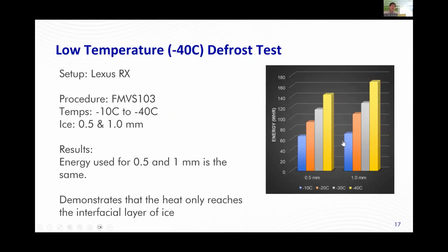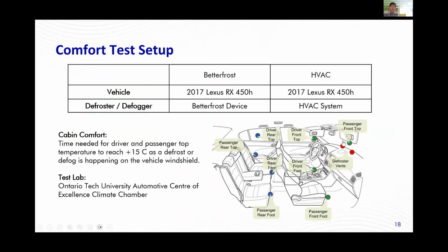We've also tested this down to minus 40 C at the Ontario Technical University's ACE climatic chamber in Oshawa, Ontario. And at minus 40 C, we've removed 0.5 millimeter and 1 millimeter of ice. What's really interesting about this, if you look at the amount of energy to be removed at the two different amounts of ice at the different temperatures, you'll see the energy is almost identical. And that is a sign that our technology is working, that the heat is only reaching that interfacial layer. So we have other tests where we show the amount of energy necessary to remove the ice is not dependent on the thickness of the ice at all. And this demonstrates that.